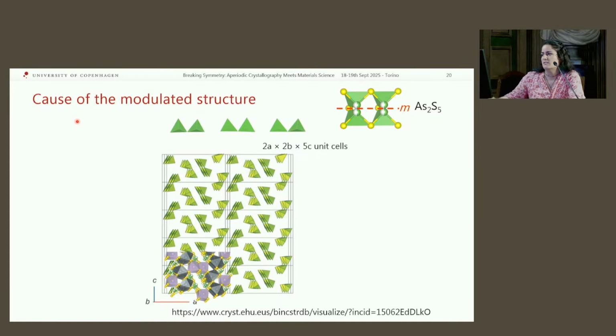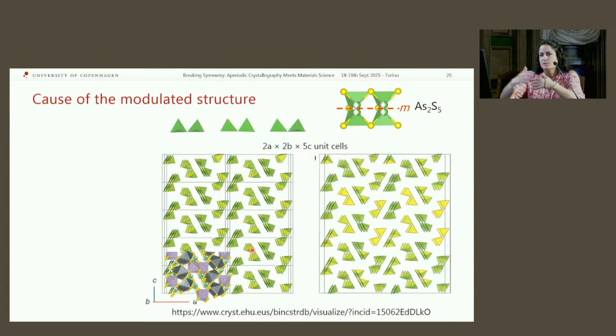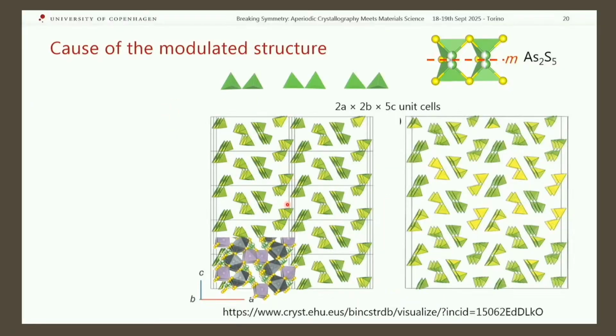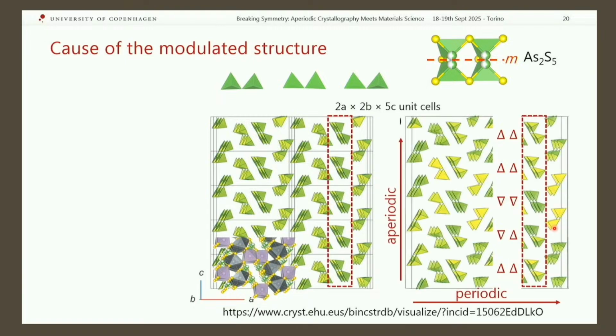And so here in the center, you see a supercell of the average structure. So to compare, we need to grow multiple cells to see actually how things change in the incommensurate modulation. And with the different lighting, you can see that different pyramids pointing up or down are differently shaded. So you can see that while in the average structure they all look the same, could be up or down regardless, here in our incommensurate model, some pyramids are up, and some pyramids are down. And there is not a clear rationale for which is up, which is down. So it's actually aperiodic in this direction, and it's periodic in the other directions.